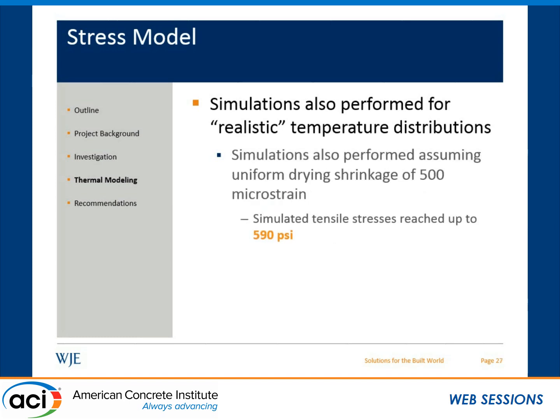The other simulation we performed was to look at the effect of a uniform drying shrinkage of 500 microstrain. This would typically happen much later in the bridge deck life, obviously, not in the first 3 days. But in this case, we found that the tensile stresses under this assumption could reach up to almost 600 psi, which is very much closer to the tensile capacity of the concrete. And remember, these are additive, so if we have a thermal effect and a drying shrinkage effect or an autogenous shrinkage effect, those strains are going to add to one another and the stresses will more closely approach the tensile strength of the concrete.